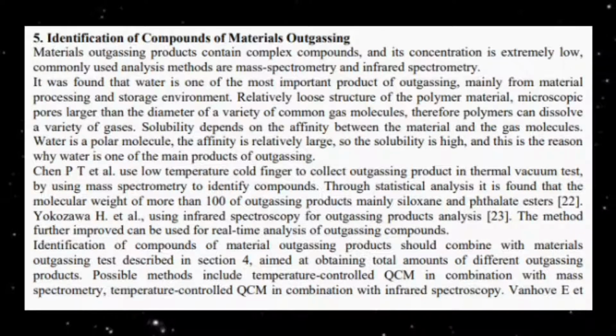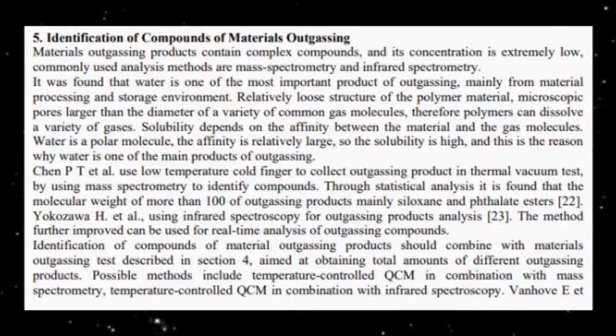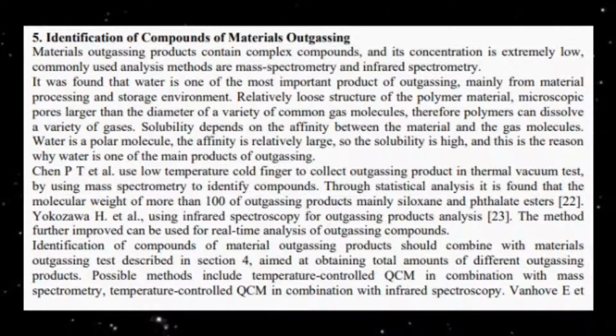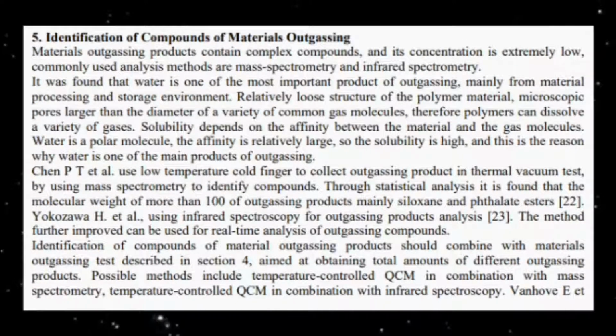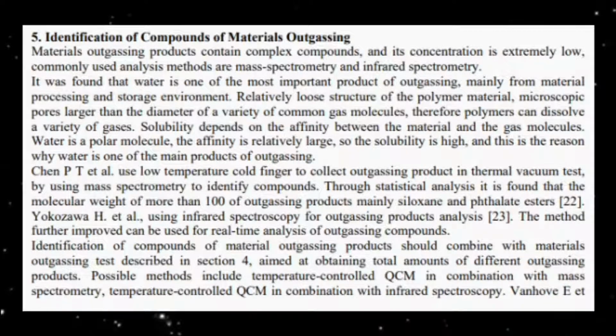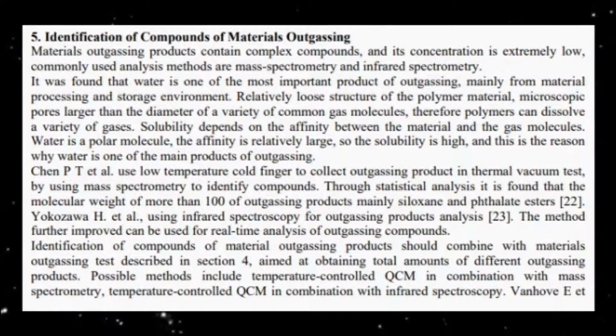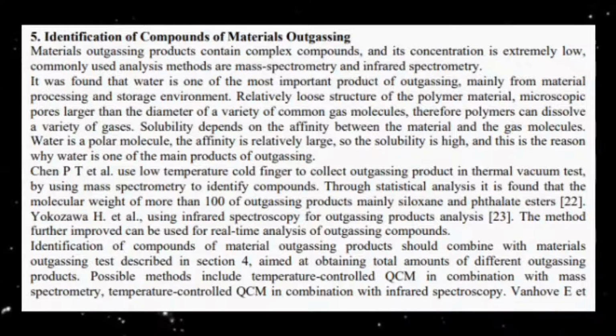Chen P.T. et al. used a low temperature cold finger to collect outgassing products in a thermal vacuum test, using mass spectrometry to identify compounds. Through statistical analysis, it was found that the molecular weight of most outgassing products is more than 100, mainly siloxane and phthalate esters. Yokozawa H. et al. used infrared spectroscopy for outgassing product analysis. The method, further improved, can be used for real-time analysis of outgassing compounds.